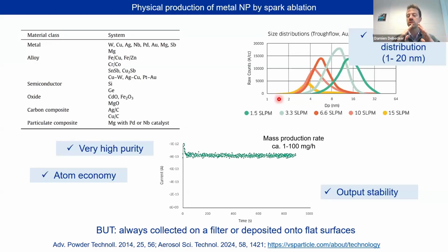And as the size distribution is relatively narrow, you can think of designing fundamental studies that could be quite interesting. And also they have quite a good production rate that is very stable in time. What I would like to focus on is the control on size and the purity, because you don't have anything else. If you want to make copper nanoparticles, you just take a copper electrode and you will form pure copper nanoparticles. You don't have any additives, salts, solvent, whatever. So in terms of atom economy, it's also good for the preparation of your catalyst. You don't use anything else.